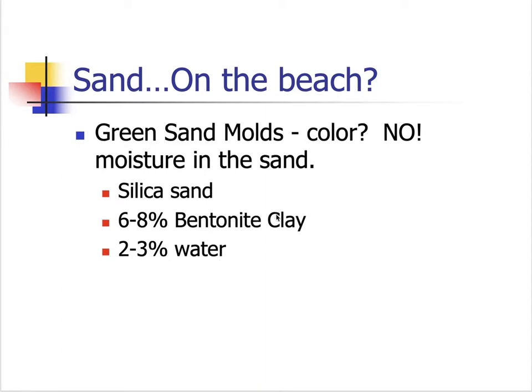Now, bentonite clay is used in a lot of applications, one of them being drilling operations where they put bentonite clay down around the drill to support it, and also to help bring up the particles of rock that are ground up when you're doing drilling for, let's say, oil. Anyway, so 6 to 8% of this bentonite clay and 2 to 3% water. Typically, the ratio between clay to water is 1 to 3, or 3 to 1 if you do clay to water. Okay, if you put too much in, the sand will be kind of wet and stick to the surface of the pattern. If you put too little in, you won't have enough strength. So the resulting castings might have a bad surface finish if you put too much water in, and if there's not enough, it will fall apart.